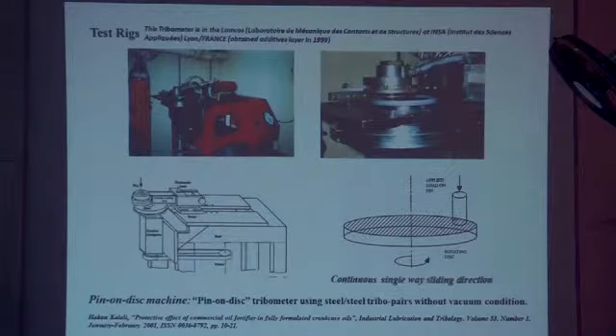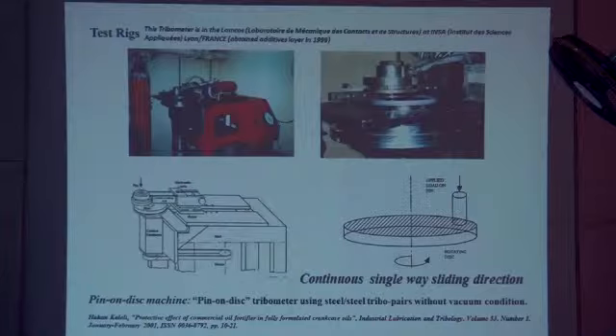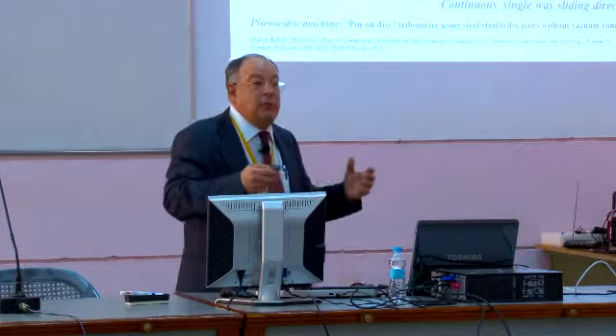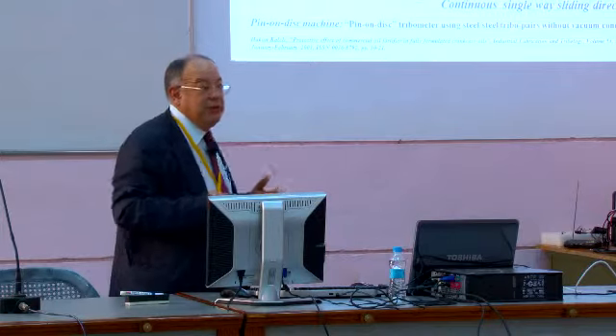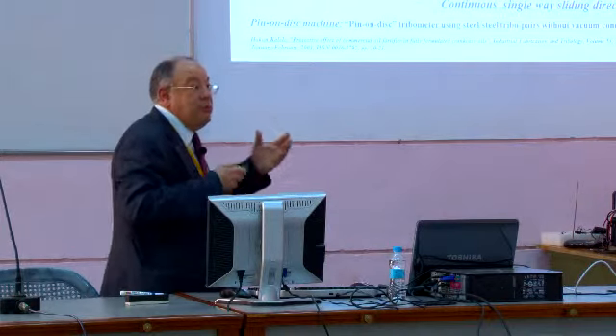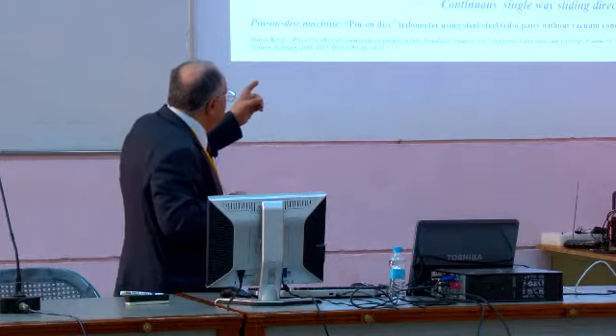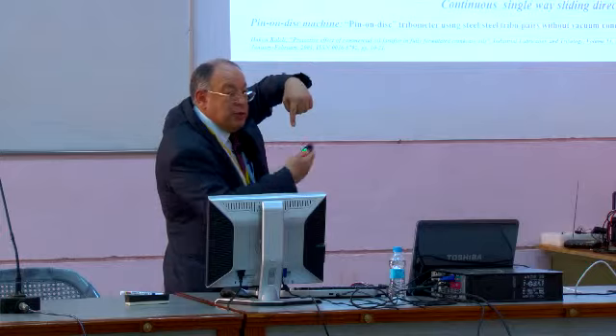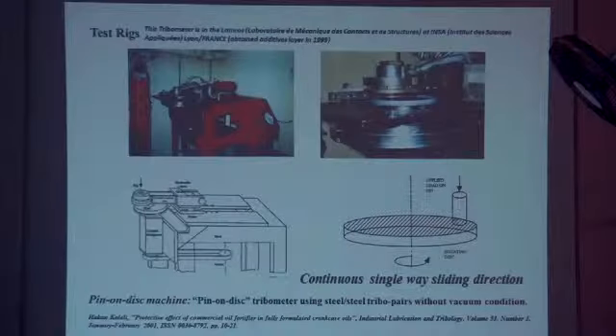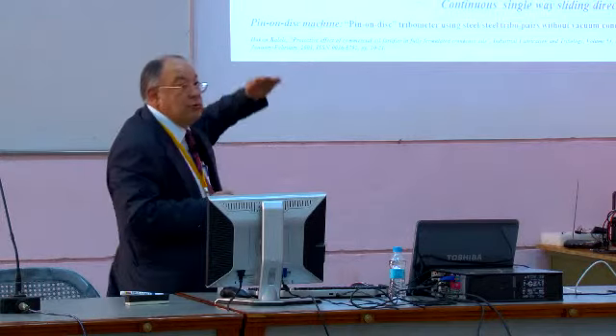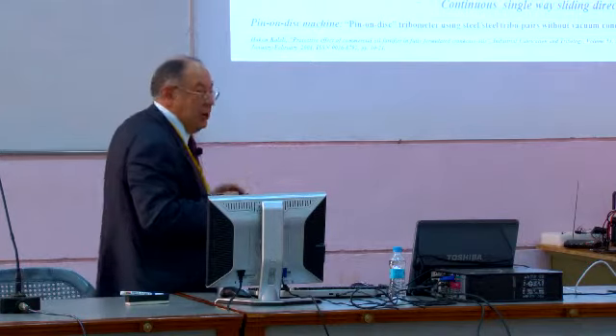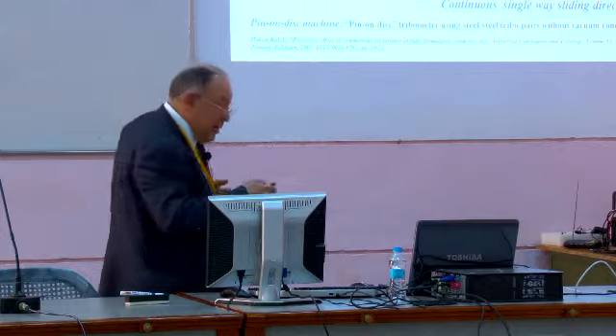I would like to take your attention, because it's very important. If you do the same test on a pin-on-plate machine, you don't get additive layers. But with the pin-on-disk machine, we did more tests with lubricant and additives. That time, oil 45 was very famous, etc. We wanted to see the friction behavior and surface analysis. On pin-on-disk, when the disk turns around, it's a continuous movement, it doesn't stop. But in an engine, it stops at top dead center and bottom dead center for a short time, and this affects the layers on the surface.